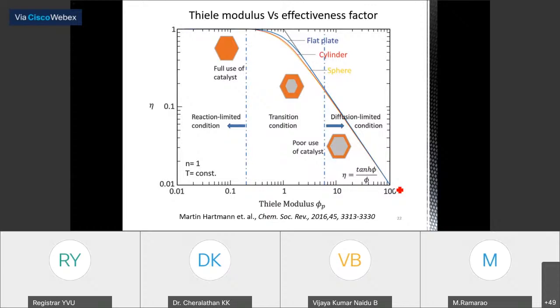And based on the position in the graph, you can tell whether you have achieved a reaction limited condition or a diffusion limited condition. In the case of reaction limited condition, the reaction is not controlled by diffusion limitation. When a reaction is taking place, there will be an active site which is catalyzing the reaction, and it should be limited to that.